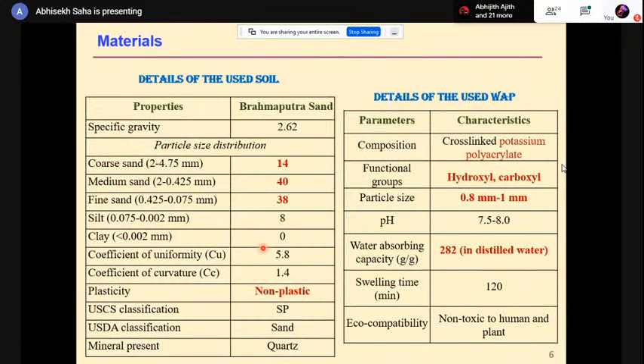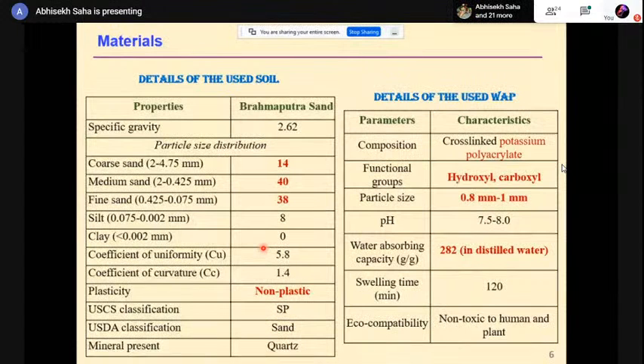So we have selected one soil. This soil is collected from the Brahmaputra river, and the main constituent of the soil is sand, and it is non-plastic in nature. The purpose of selecting a non-plastic soil is that it is reported in the literature that the performance of the polymer is best suited for cohesionless soils. That's why we have taken a cohesionless soil, and we have used a potassium polyacrylate water absorbing polymer. Its primary functional groups, analyzed using FTIR, are hydroxyl and carboxyl, and the water absorbing capacity is around 282 gram per gram in distilled water.